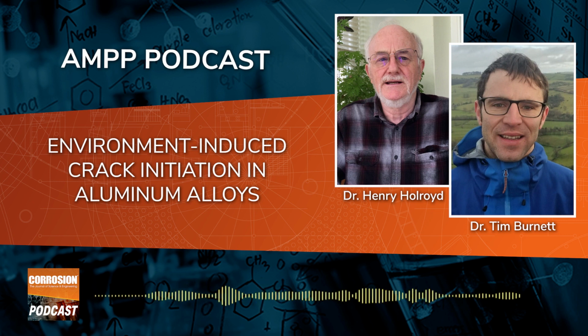You need a microstructure that's susceptible. You need an environment that gives you the right type of attack, and you need the right stress conditions. It varies from alloy to alloy what the best combination is, but we find some alloys will crack in water vapor, and they tend to be the stronger ones and the more modern ones. Those, for instance, would not crack particularly well in aggressive saline solutions. Several factors are important for initiation. So initiation is a subset of environment-sensitive fracture, and so we have concentrated in these two subsections on the initiation phase. So I hope that helps.